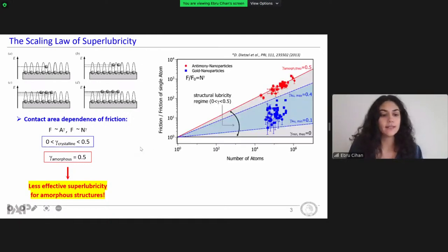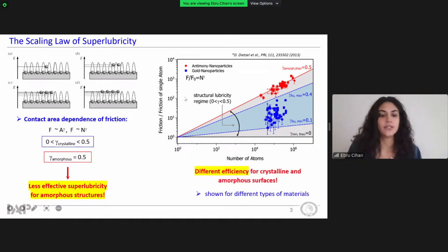Previous experiments with crystalline gold and amorphous antimony nanoparticles confirmed this theory very well. That is, a different efficiency is demonstrated for crystalline gold nanoparticles, where lower friction is achieved. This result is actually very good, but not sufficient for an atomic-based explanation of superlubricity, because it has been demonstrated only for different types of materials.